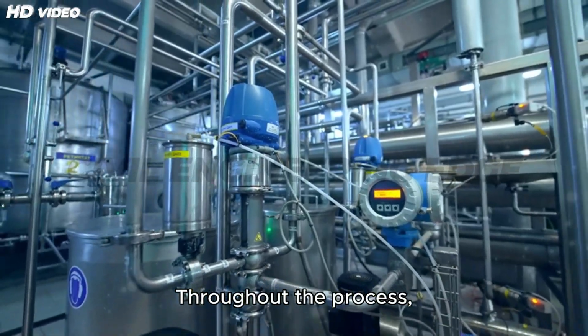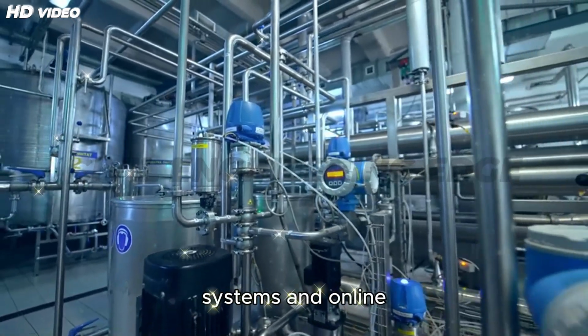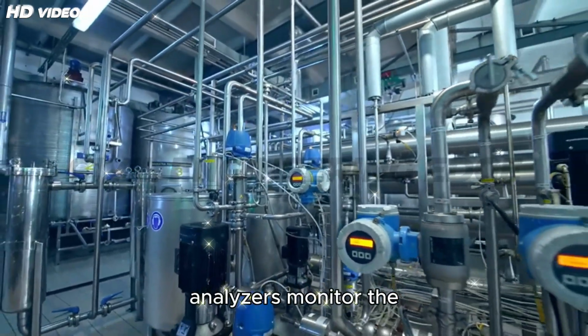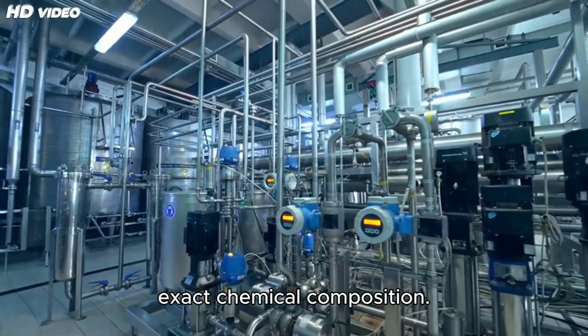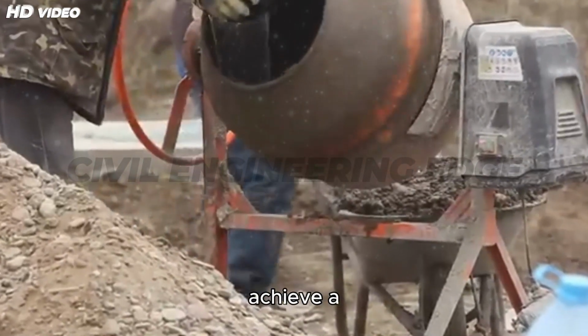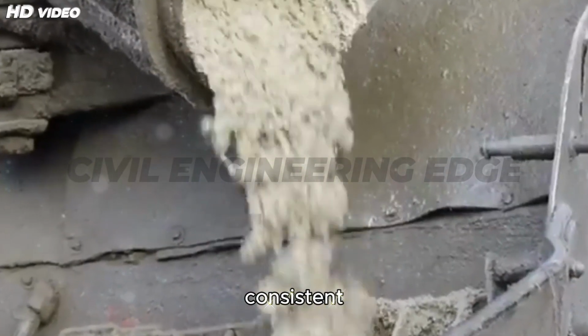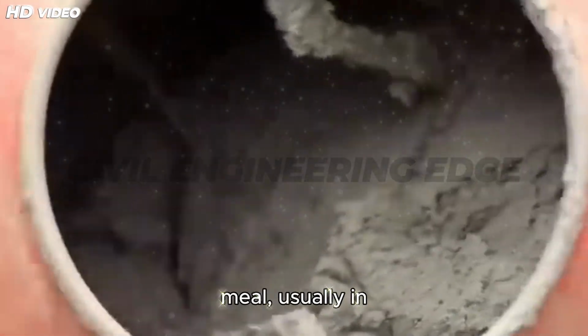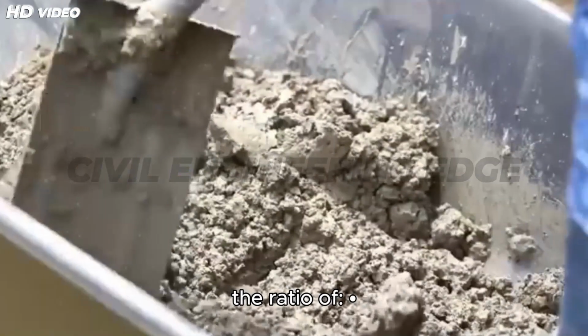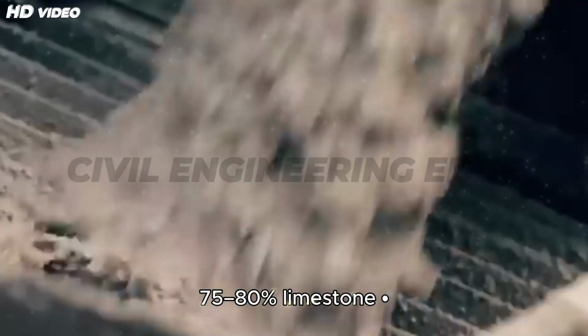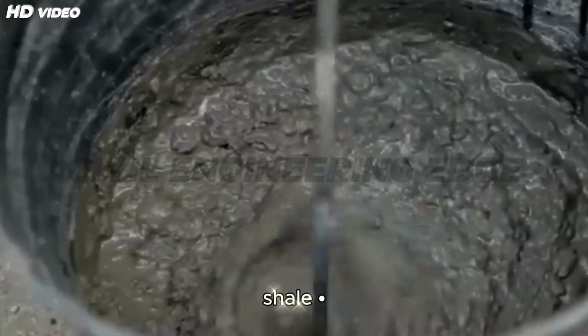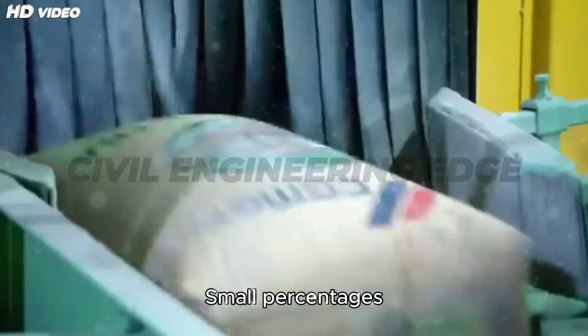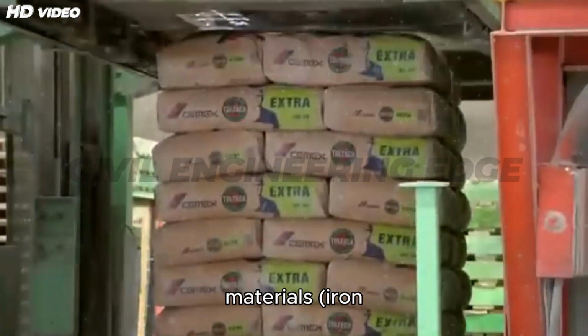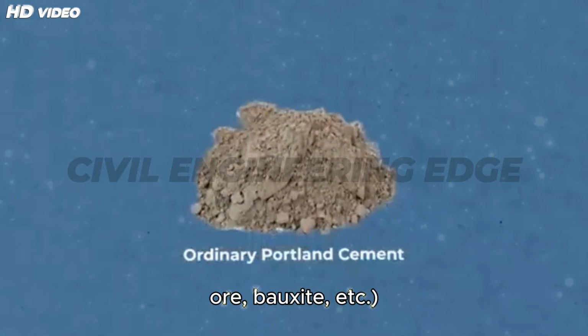Throughout the process, automated weighing systems and online analyzers monitor the exact chemical composition. The goal is to achieve a consistent proportion of raw meal, usually in the ratio of 75 to 80% limestone, 20 to 25% clay or shale, and small percentages of corrective materials, iron ore, bauxite, etc.